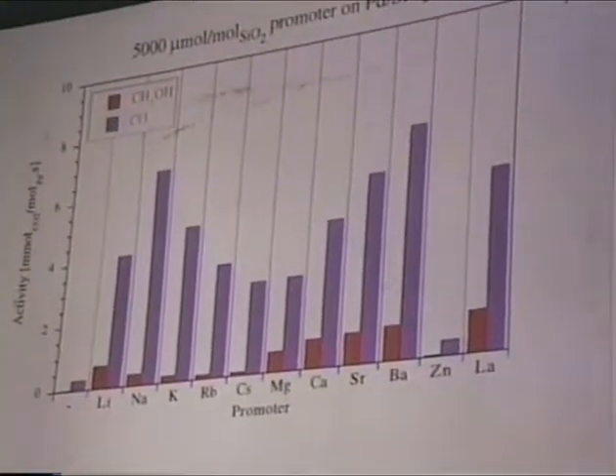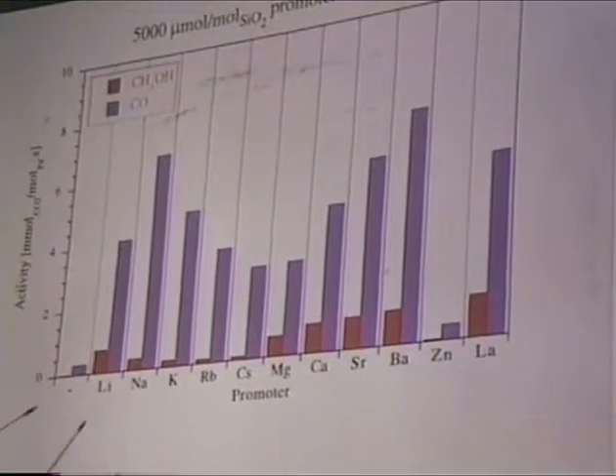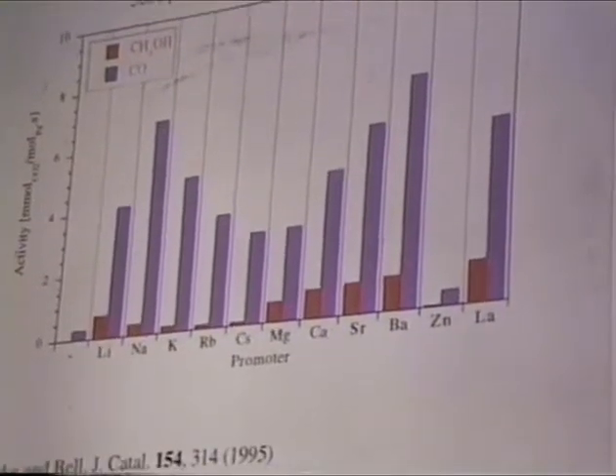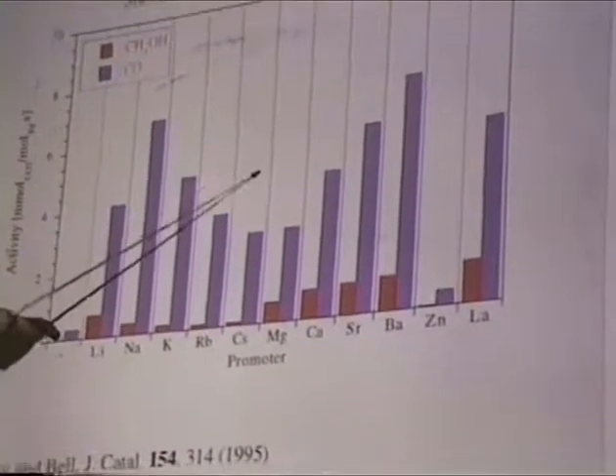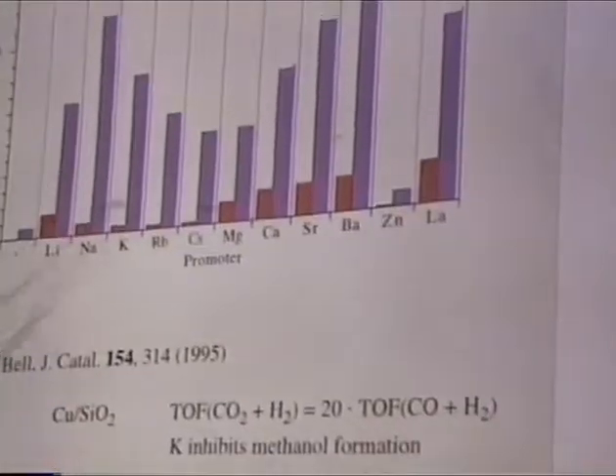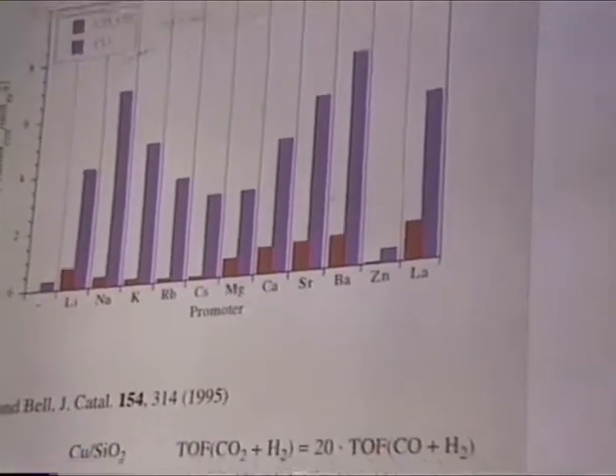In our case, the palladium alone on the silica, it does show with the CO2, it does show CO, so you get somewhat of an activity for the water gas shift, for the reverse water gas shift. But there's no activity for the methanol. So it's not comparable to the copper case. However, if you promote it with these basic promoters, then the water gas shift goes up tremendously, and at the same time you see methanol formation.